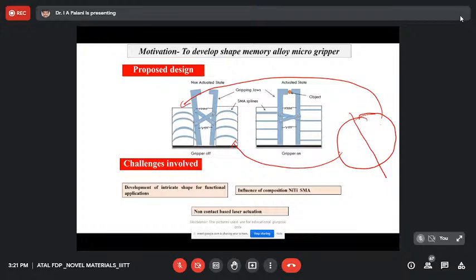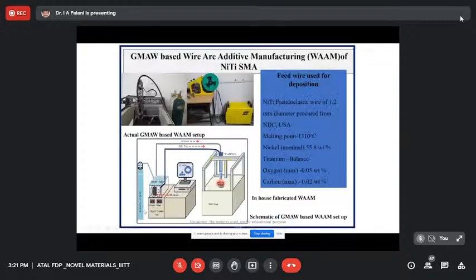Okay. So in order to fabricate such kind of structures, we developed a small experimental setup in our laboratory. In fact, we developed a small additive manufacturing setup in our laboratory, which we call wire arc based additive. In this wire arc based additive, what we did is, we took a small gas metal arc based welding unit. We manipulated the gun. We developed our own code.